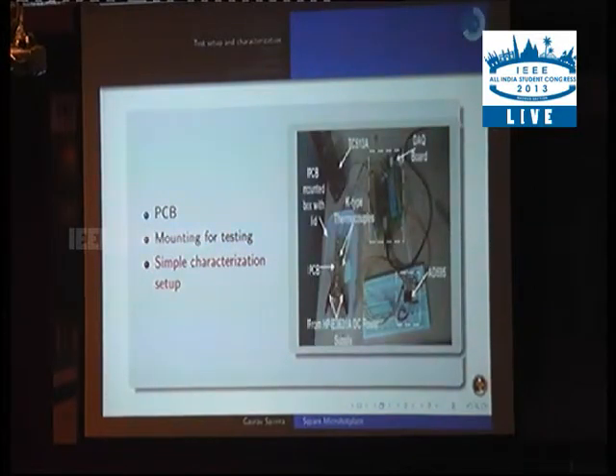So this is the testing setup we made. This PCB which we have prepared is sitting here. It is supplied by a DC power supply. Using a K-type thermocouple, we are measuring the temperature of the micro hot plate. It goes to a DAQ board, and then we have a Visual Basic program which records the signals. So it's a very simple characterization setup we have built.